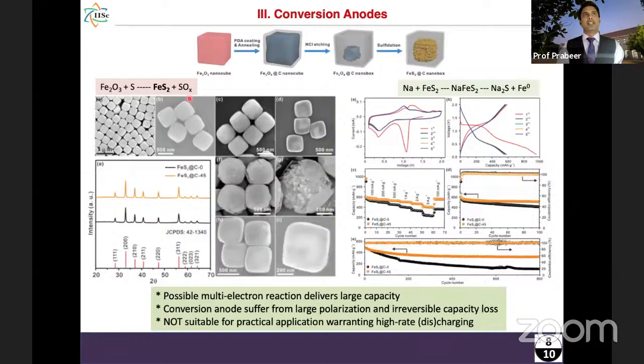Basically we can use iron oxide nanocube, and we can react this iron oxide with sulfur gas. If we react iron oxide with sulfur, it forms sulfate gas and iron sulfide product. This iron sulfide product can give rise to different morphology. When we react this with sodium, sodium can interact with this iron sulfide or pyrite to form NaFeS2, and subsequently it can decompose to form Na2S and metallic iron. And this can go back to the system during charging and discharging.